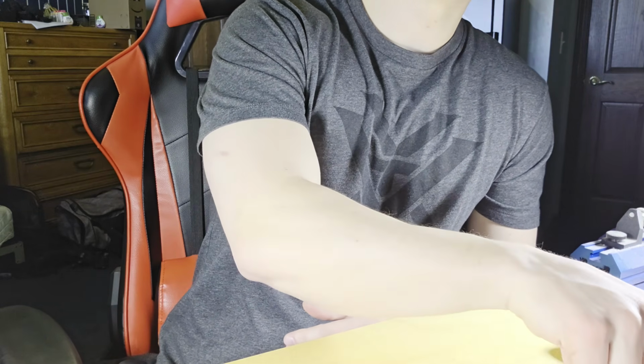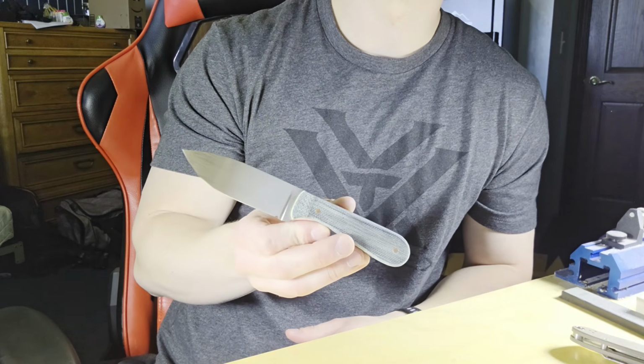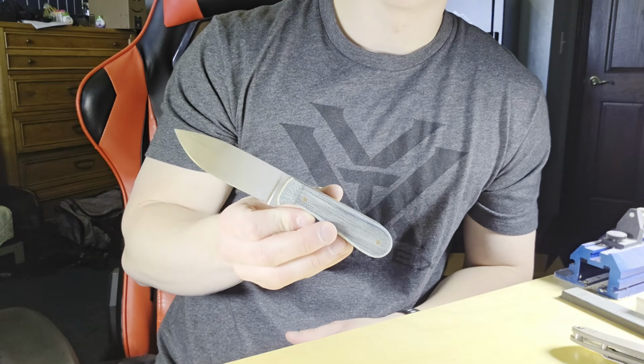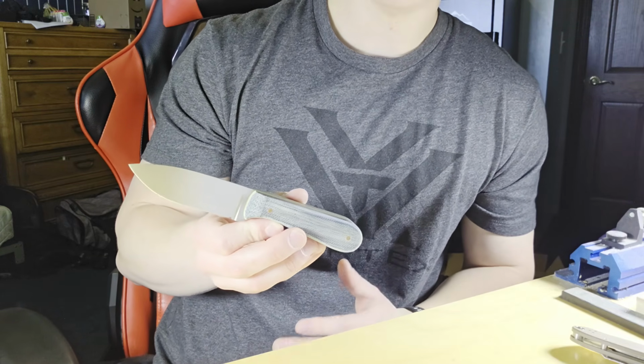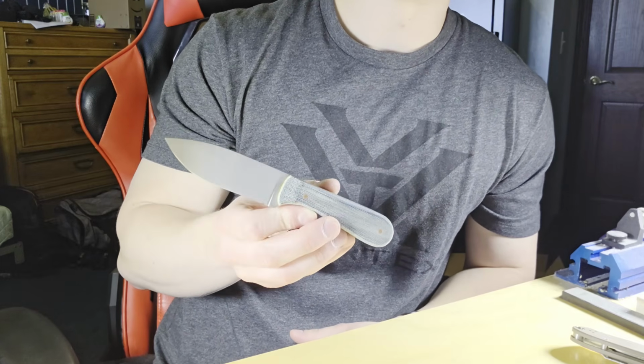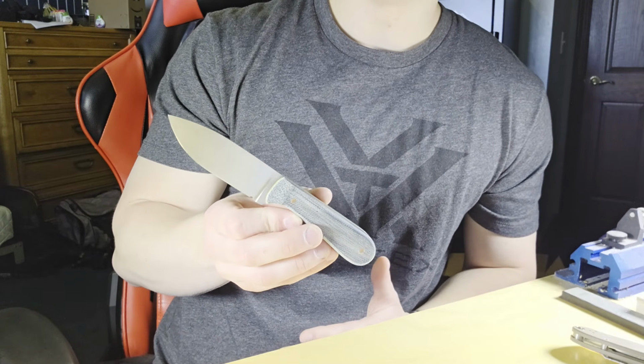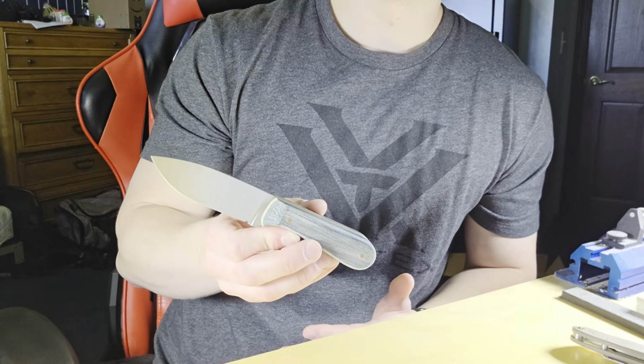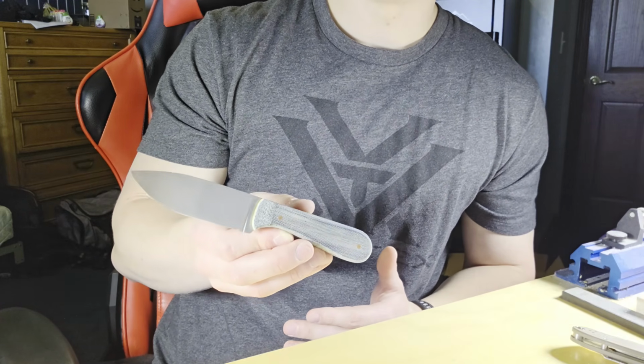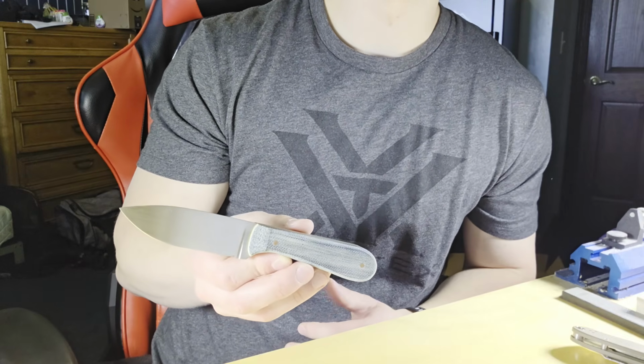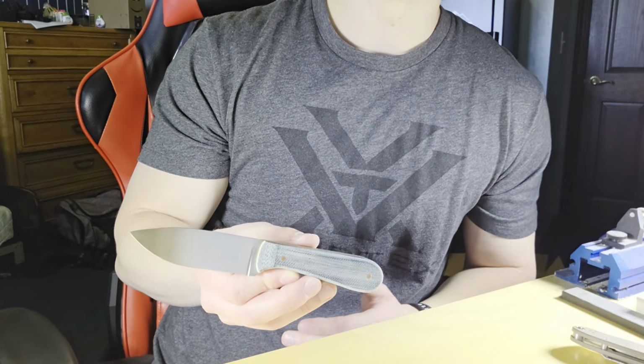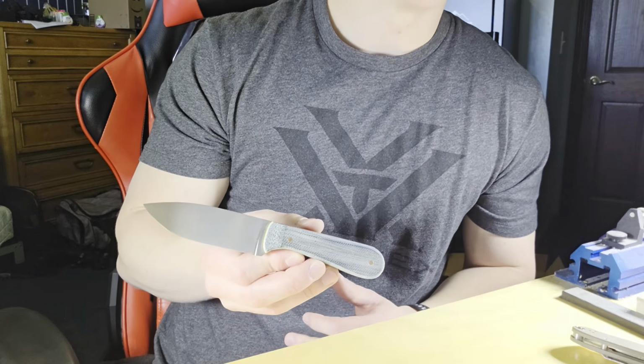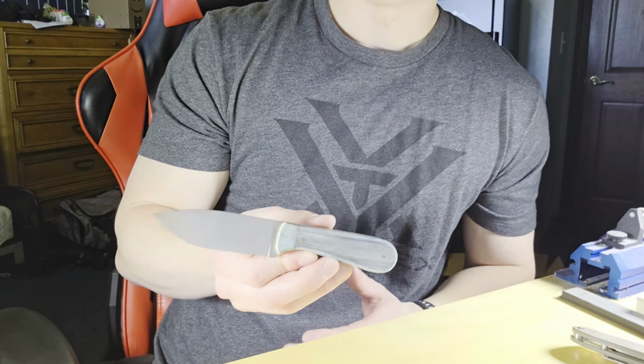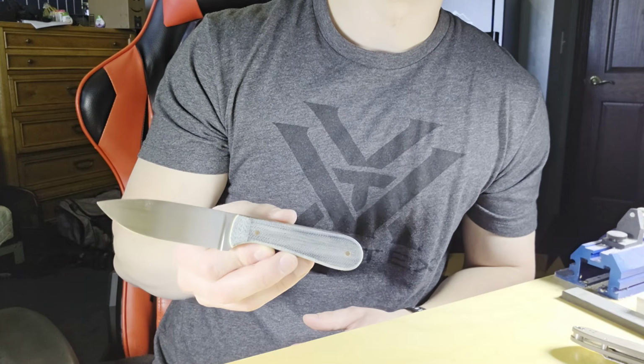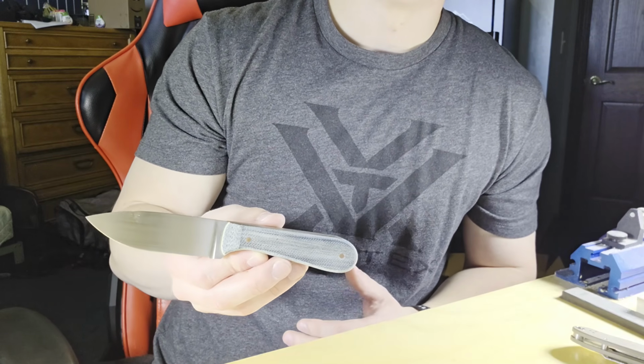Now there's two examples I have here. Number one, I think, is a steel like this. This is 8670. This is just a plain carbon steel, really about as basic as you can get. On Larrin's charts, it is the lowest edge retention steel, but that's because it's run at a low hardness. It really doesn't have super high attainable hardness, but it also has super low carbide volume, and the carbide type is just cementite, which is just iron carbide. It's the softest carbide type there is. So in this case, the carbides may not be crazy important. If you run this at a higher hardness, like this is 63 HRC, you're going to get better edge retention out of it.